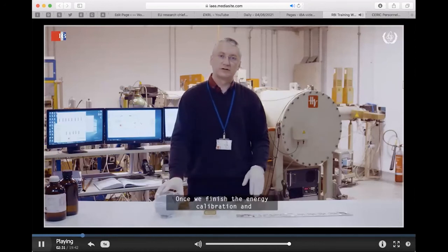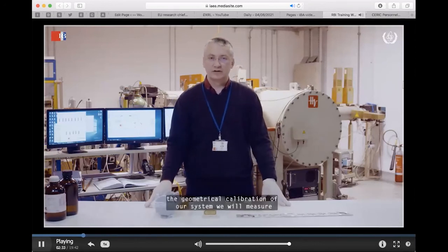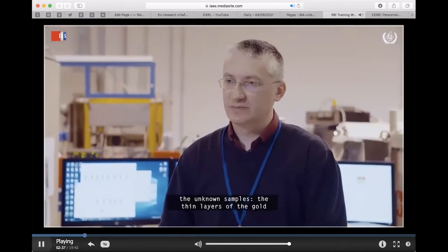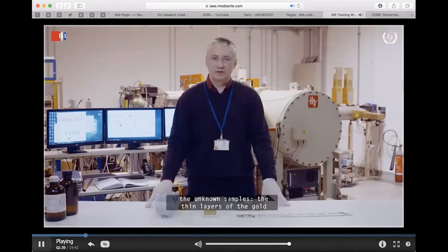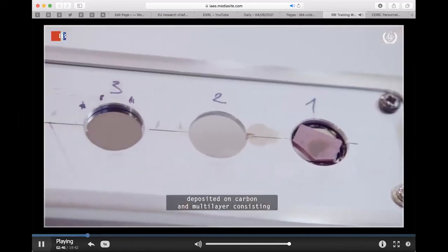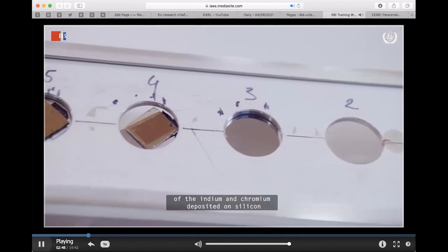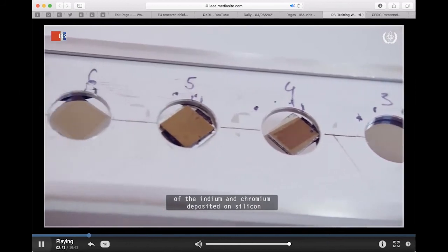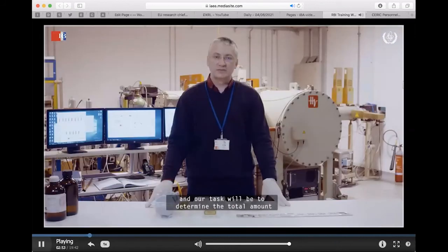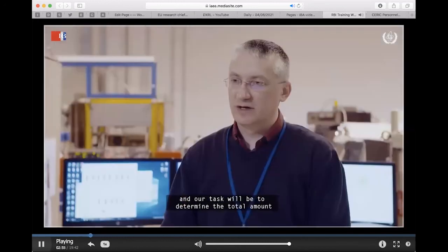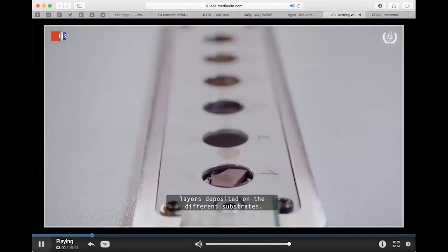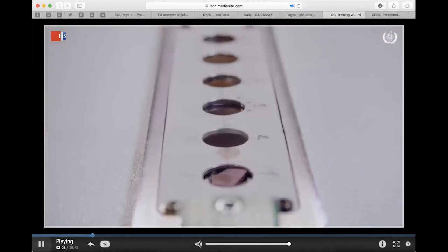Once we finish the energy calibration and the geometrical calibration of our system, we will measure the unknown samples: a thin layer of gold deposited on silicon oxide, a thin layer of gold deposited on carbon, and a multilayer consisting of indium and chromium deposited on silicon. Our task will be to determine the total amount of gold and the total amount of indium and chromium layers deposited on the different substrates.